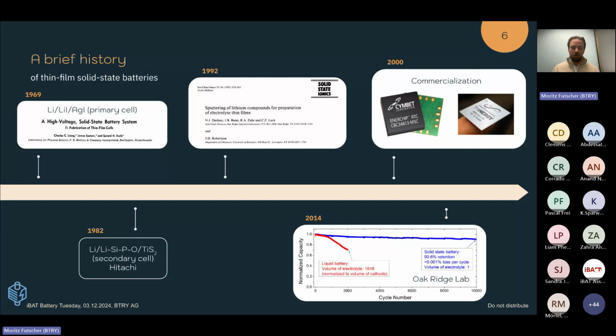Most of them are not around anymore, with the exception of two, which have been bought successfully along the way. One was bought by Apple, and one was bought by Dyson. And then another milestone and important fabrication to mention is also by the Oak Ridge National Laboratory, the same lab that developed this solid-state electrolyte. They showed that they could successfully cycle for more than 10,000 cycles, and still after 10,000 cycles have a capacity of 90% of the original capacity.